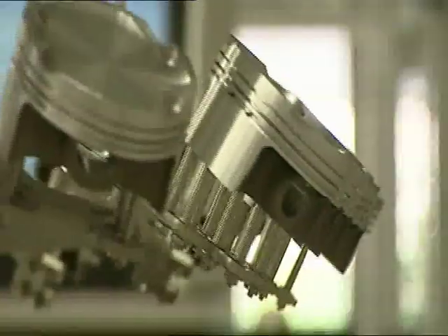Reliability in motor racing is extremely important. Therefore, we crack test our race pistons 100% with our dye penetrant crack test method. In order to do this properly, we need total darkness. Darkness is needed as a luminous agent is applied to the pistons. This enables even the tiniest cracks or bumps to be seen.